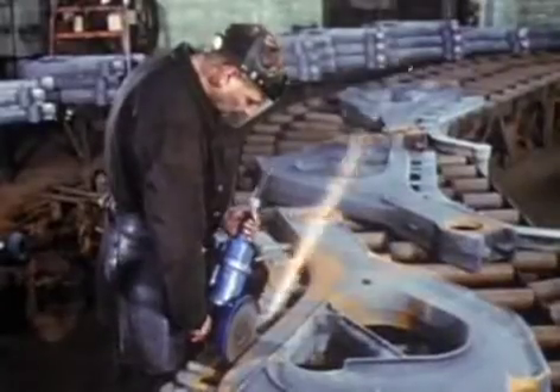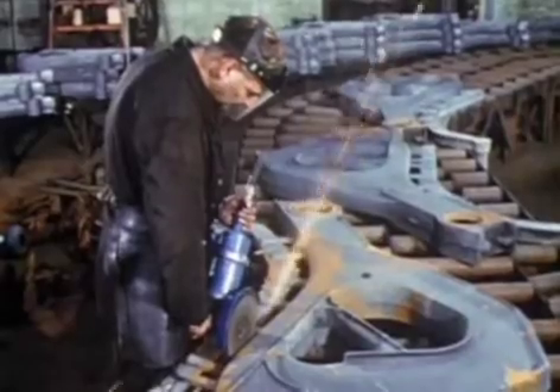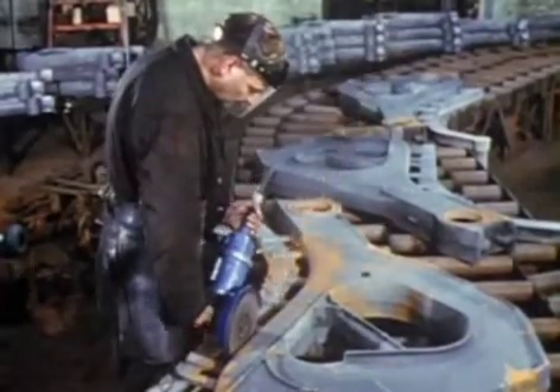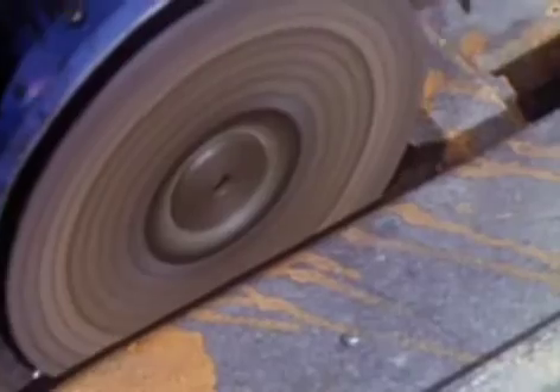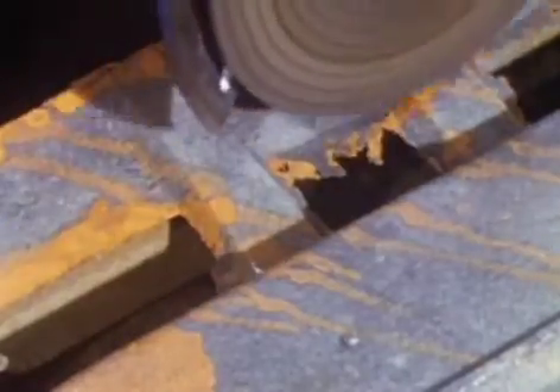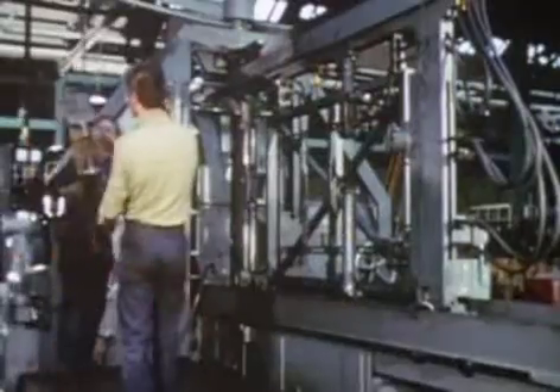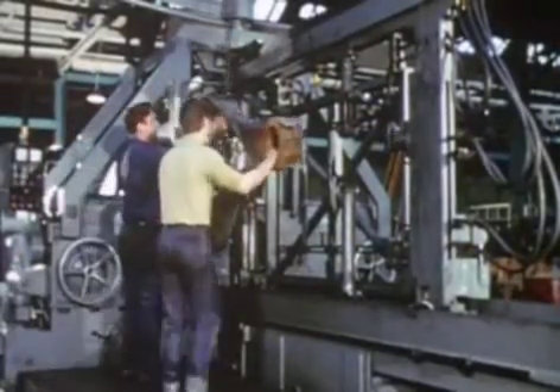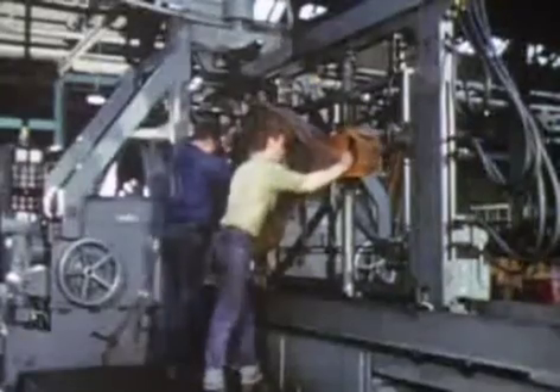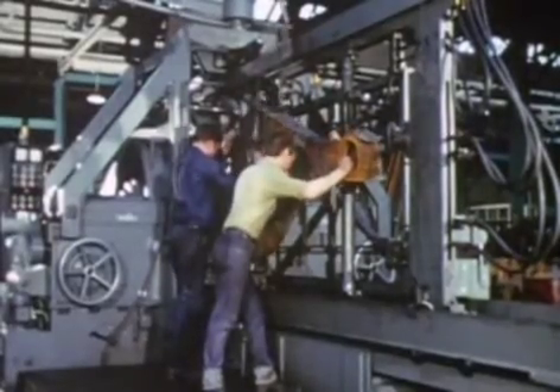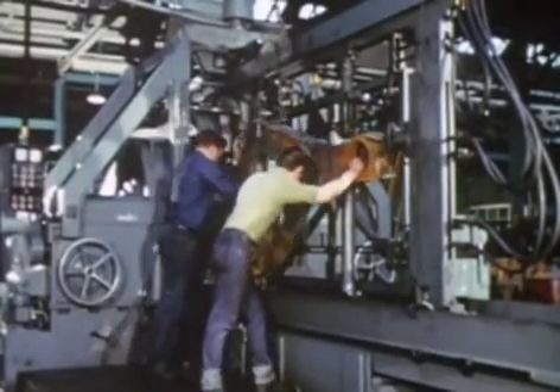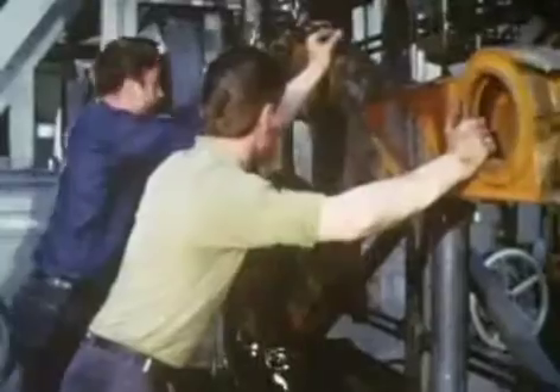Let's return to the production of SG iron boiler sections. They're produced on a flow basis. Here the runner bar is removed by high-speed carborundum saws, leaving the casting ready for its first pressure test. After testing, the casting moves on to the high-speed grinding machines where the section beads are accurately ground, thus ensuring gas-tight joints between the sections on the final assembly.